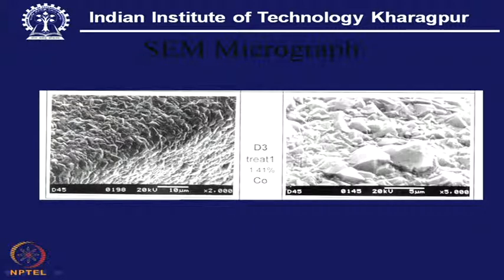So, this SEM picture can reveal so many things apart from the crystal size, the uniformity, the void density, and it can clearly show this outgrowth. If there are certain pinholes, it can also happen during this coating deposition. Sometimes certain areas, because of very strong passivity, are not covered at all by this coating. That means this coating doesn't get attached to that, and that is called the sticking coefficient. So, this lack of sticking coefficient can also make some pitting or void there, but that can also be recorded by this SEM.